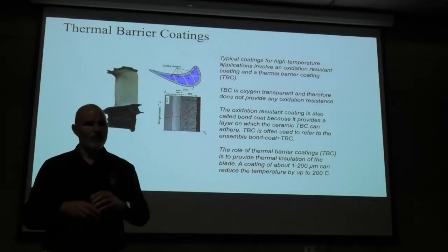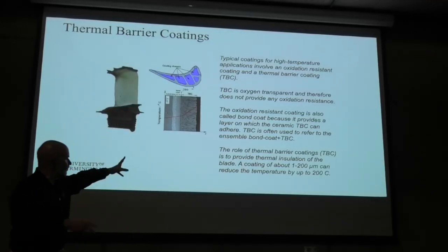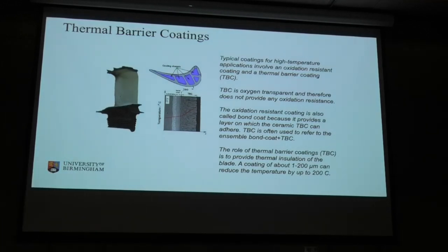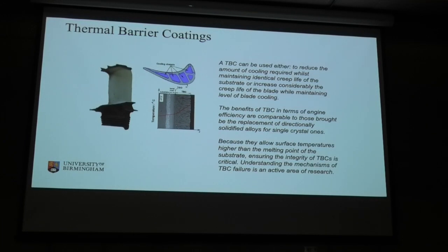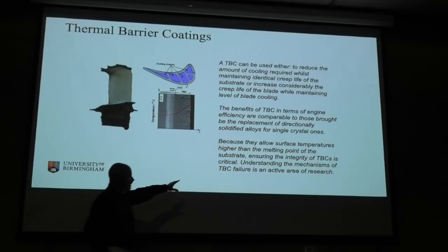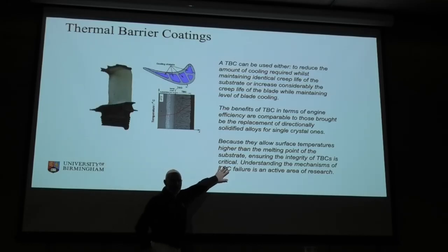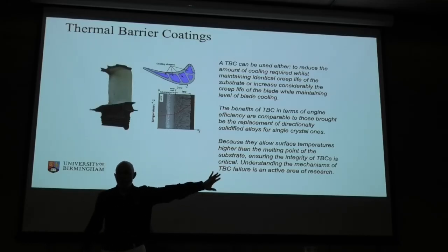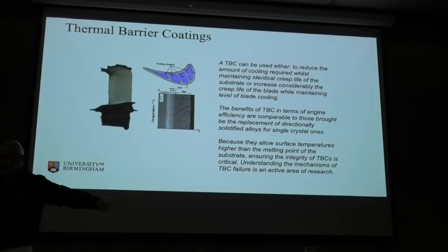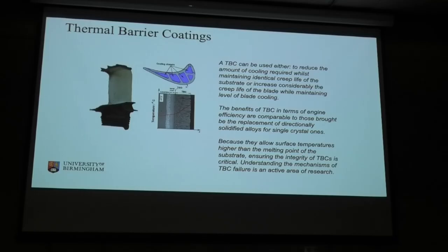And so we end up with these components where we've got lots of things going on to make sure that at the end of the day, everything survives. Understanding why these things fail, often we'll lose the thermal barrier coat and we'll burn through the blade, and that's why things get taken off wing after 10 million flying miles. It tends to be things like that, the loss of the barrier coats, that actually mean that we're going to replace after however many - 5,000 flights.